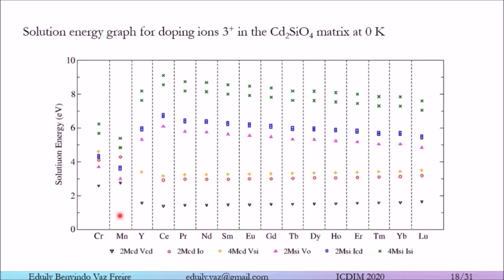Okay, now we have the graph for the Cd2SiO4 matrix at 0 Kelvin. In this graph, we see that doping with rare earths follows the same pattern seen for the CdSiO3 matrix. However, there is a big difference for the transition metals, because in this matrix we observe that they also enter the cadmium sites plus a cadmium vacancy, which was not expected from the CdSiO3 matrix.